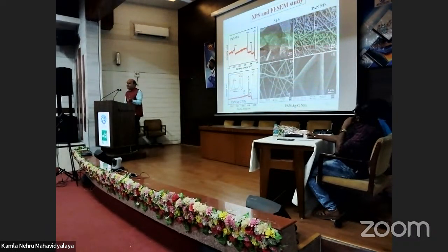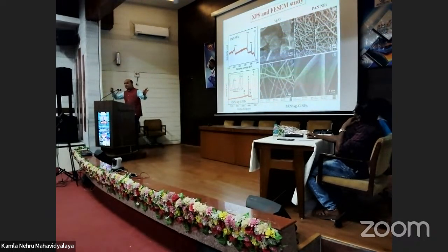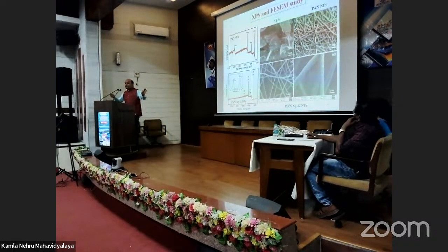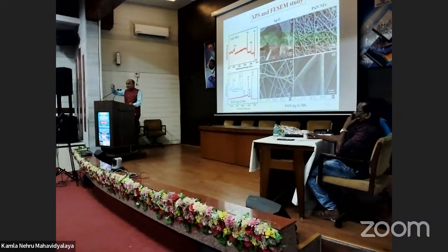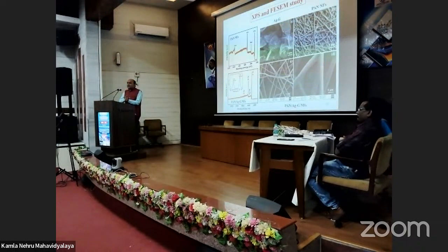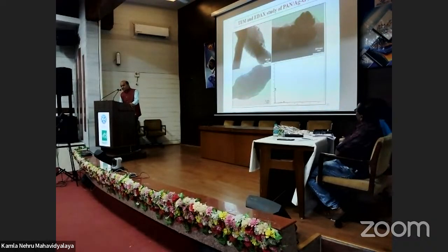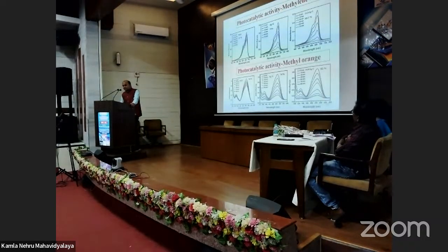Why do we call it a nanofiber? The length cannot be in the nano form, but the diameter of the fiber is in the nano form. And the porosity there, the pores inside those fibers, are also nano in size. And in those pores, we have decorated the silver graphene oxide nanoparticles. So this is a porous, bone-like structure, and this is the photocatalytic activity of the material we have tested.